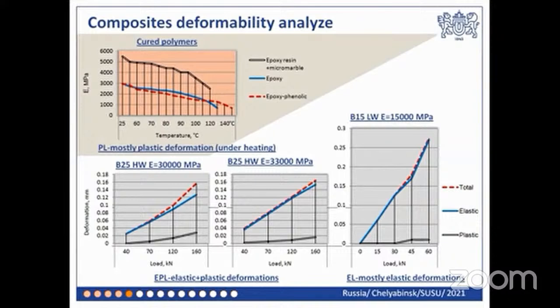It can be noticed that there are traditional viscoelastic characters of concrete stress-strain conditions, but it's necessary to pay attention to plastic deformation of different concrete types. The heavyweight concrete with high elasticity modulus had less plastic deformation than usual, and lightweight concrete has in fact no significant plastic deformation under compression. So the main factor of composite viscoelastic properties is the volume and elasticity level of ITZ.